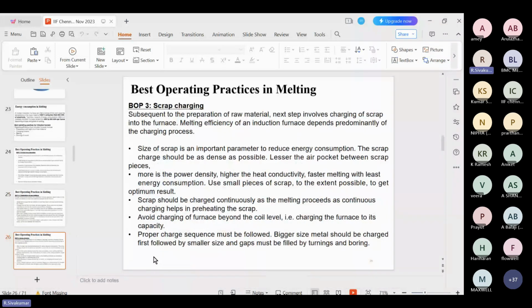Scrap charging: subsequent to the preparation of raw material, the next step is charging the scrap into the furnace. The melting efficiency of the induction furnace is predominantly based on the charging process also. The size of the charge is an important parameter to reduce consumption, because the scrap charge should be as dense as possible, so that air pockets between the scrap pieces are minimized. That gives more power density and higher heat conductivity. It leads to a faster melting rate, and ultimately the energy consumption is also reduced. Use as many small pieces of scrap as possible to get the optimum result. These are some practices to be adopted on the shop floor and in the melting area itself.